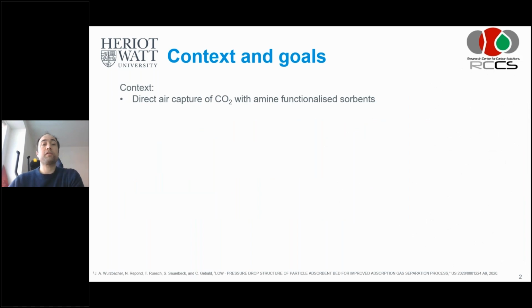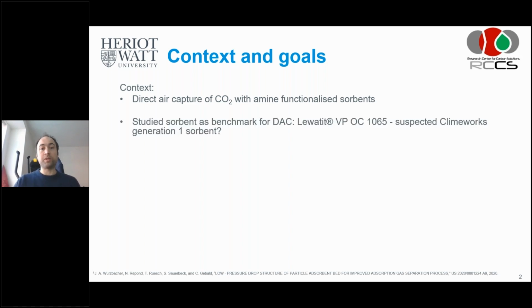So first, a little bit of context. So what is it that we are doing? We look at direct air capture of CO2. So we try to suck CO2 out of the air with amine functionalized adsorbents. And the reason why we like amine functionalized adsorbents is because they bind CO2 very strongly, especially in what we call the Henry regime. So the very low partial pressure regime of CO2,